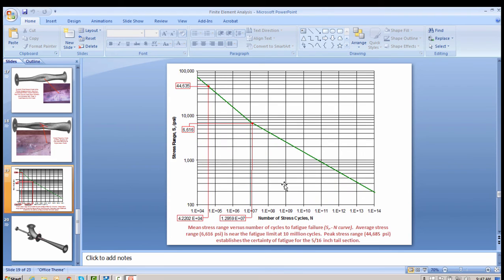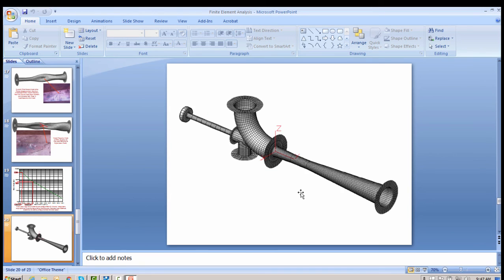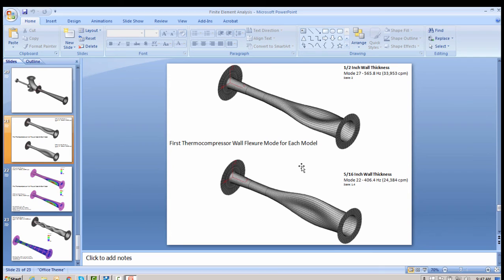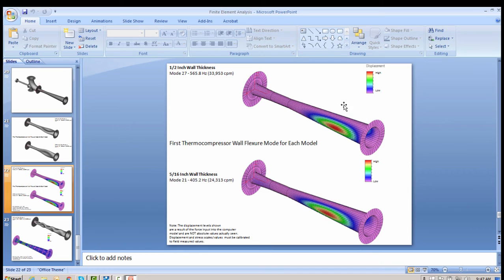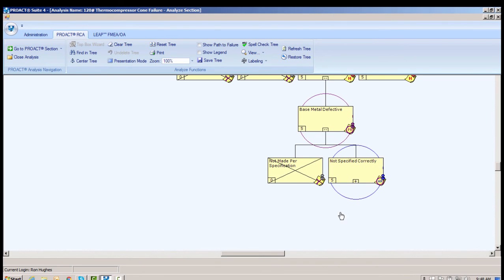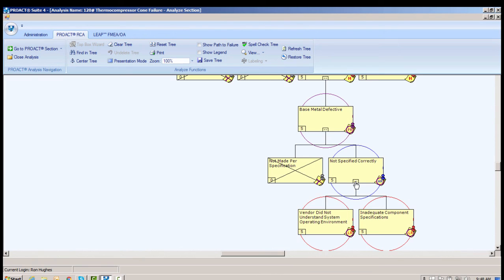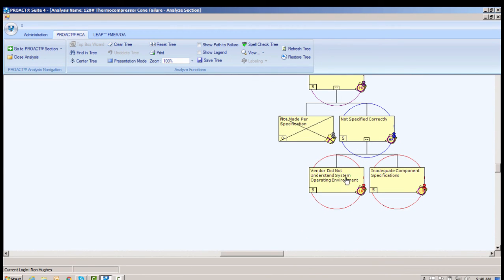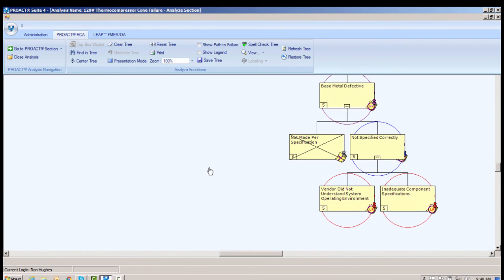Okay, and then of course, this is the stress strain diagram and the number of cycles that we're using. We're figuring everything out in our model, and we compare what we're going to recommend, which is a 1/2 inch thick chromoly material, to what was actually supplied, a 5/16 of an inch carbon steel material. And we determined that, using our model, our 1/2 inch chromoly plate will definitely work for the situation that we're trying to operate in. So not specified correctly, because the vendor didn't understand the system operating environment, and we have inadequate component specifications for the Thermo-Compressor code.